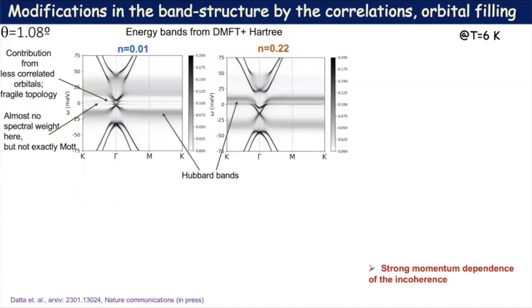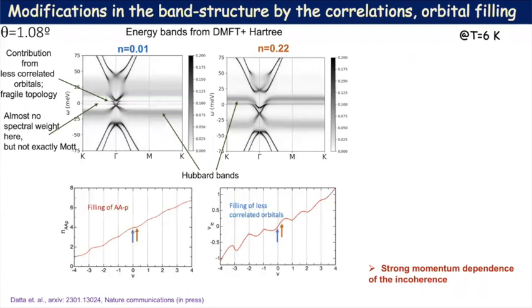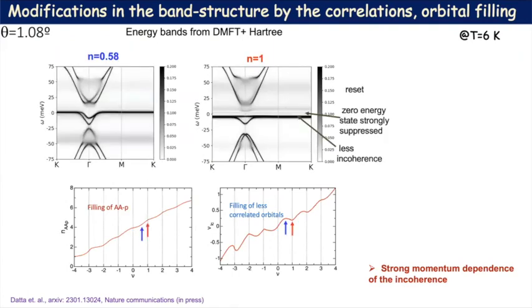One thing is that there is a strong momentum dependence of incoherence because of this fragile topology. And then if you look into the fillings of different orbitals, you can see that there's a plateau here because the filling is happening in the less correlated orbitals, and there is an increase here in this figure. This continues until the upper Hubbard band gets pinned to the 0 energy, and we now have mostly the AA-p orbitals at this 0 energy.